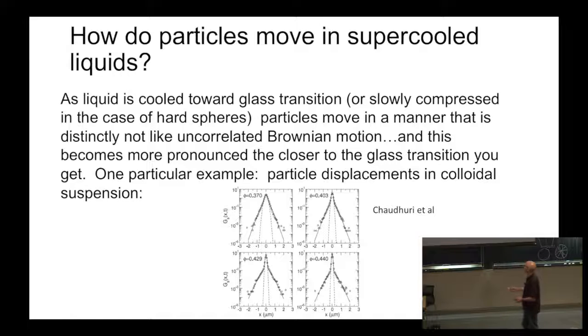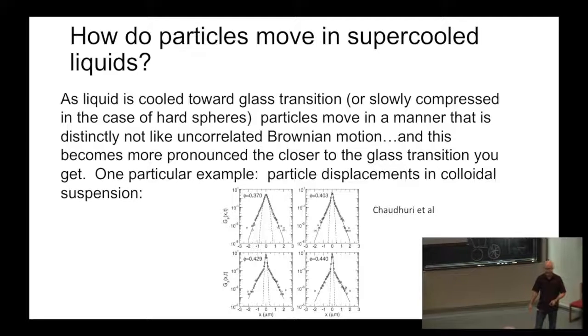And so basically, if you look at the probability for a single particle in your sample to displace a distance x in a time t, that's related to this function, which is called the Self-Van Hove function. And at low densities or at high temperatures, a large portion of that displacement probability distribution density is Gaussian. And what you start to see as you get closer and closer to the glass transition is that these fat, potentially exponential tails of the distribution get more and more palpable as the system gets closer to vitrification.